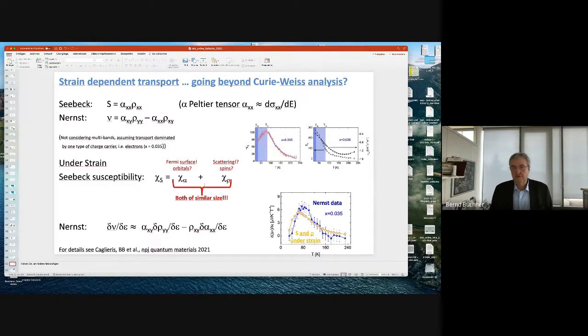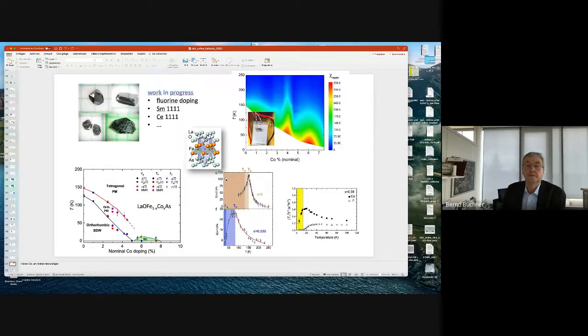And you can even do a cross-check by measuring the Seebeck effect and resistivity. We can put it into this formula, and then we can reproduce the Nernst data from that. If you want to see more details, it's in this publication. So this is the present situation where we are. We have this new phase diagram. We have the nematic instability, which becomes very large just in the same concentration range where systems become superconducting. But it's not only superconductivity, it's also a lot of normal state behavior of these systems, which is very, very funny due to this unusual instability, which is connected, I believe, to the orbital degrees of freedom